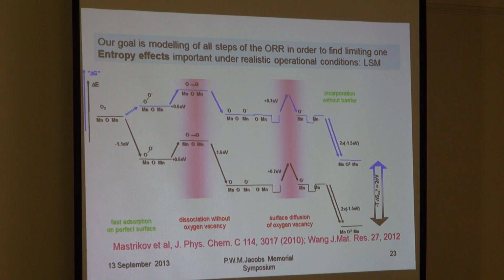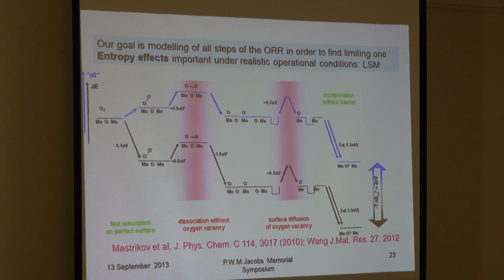So from computer modeling, we found that adsorbed oxygen ions are quite immobile. So migration energy is about 2 electron volt. Whereas surface vacancies are even much more mobile than in the bulk, and migration energy is about 0.7 electron volt. So our scenario is that surface vacancies are very mobile. They approach adsorbed oxygen atoms, and then that triggers penetration of oxygen from the surface into the first plane and into the first bulk. And the rate determining steps are shown here, essentially in pink. So it's either molecular dissociation or it's diffusion as a vacancy on the surface.